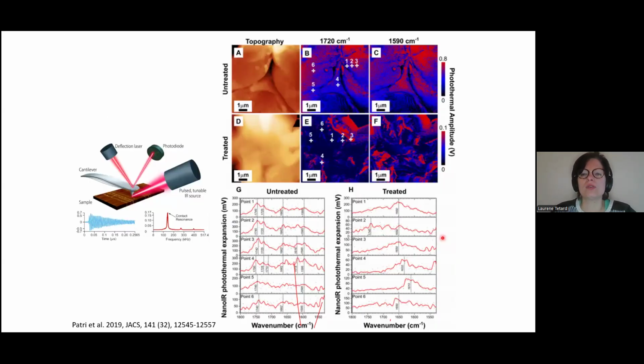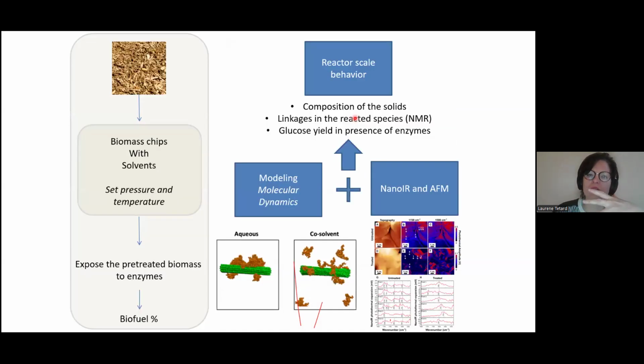But we also added the chemistry. We found that before treatment, there was a lot of C double O chemical bond in the system. And that C double O bond was gone after the treatment, and the only thing that remained was that peak here, which is indicative of water in cellulose. So that allowed us to understand what's going on. And then what we did is we worked with molecular dynamics modelers to make sense of what we were seeing at the nanoscale and combine these two, theoretical view and nanoscale view, to help the analysis of the reactor scale behavior.